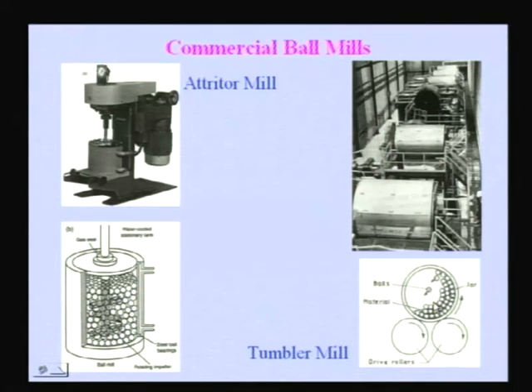wall of the tumbler mill. So, just lower than that velocity if you use, then the ball will go up to the top and then just falls from the top and gives you an impact. And here also, depending on the size of the actual container, the energy is decided by that, because the height from which the ball drops is what is going to give it the kinetic energy. So, as a result, the energy of this mill depends basically on the diameter of the ball, and at the same time it also depends on the speed at which the whole tumbler mill is rotating.